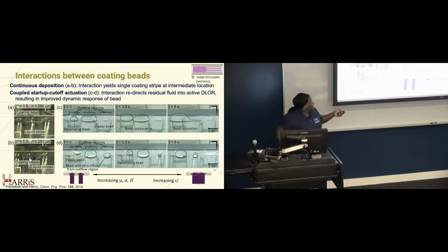Then looking at that comb-like structure, what we found here is that as the actuation is on and off, it really had a sensitivity to H, the gap between the die lip and the substrate. And what we found is that if we increase the viscosity, the surface tension, and H, then we got distinct lines. However, if we increase Q, the fluid would come back together. And so we understood from that, okay, if we control Q alone, then we'll get a split, but Q and H in concert will allow us to get the distinct lines again.